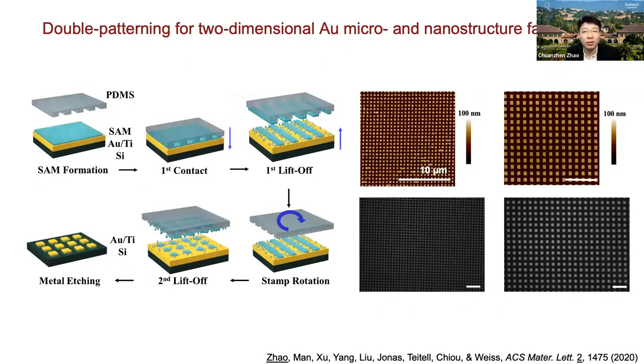Apart from 1D gold nanostructures, plasmonic 2D nanostructures were shown to have enhanced plasmonic properties, and they allow better control of their optical properties. We then developed a generic approach to fabricate 2D gold nanoplasmonic devices, also using chemical lithography. Here we demonstrate a double patterning approach, which is quite straightforward and can produce 2D features using those nanoribbon PDMS stamps, which are also made from the HD DVDs.